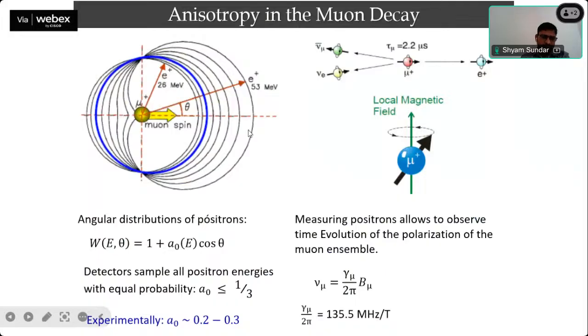When the positron comes from the muon decay, it comes at several different energies, and the angular distribution of the positron is governed by this equation, which is anisotropic. As you can see, A naught is the asymmetry parameter. This is 1 third if you have the highest energy positrons, but since we are collecting with different detectors to detect all those positrons with equal probability, A naught can be less than or equal to 1 third, and experimentally we get a value of around 0.2 to 0.3. We never achieve exactly 1 third because of some experimental limitations. But this is the brief overview of the muon technique.